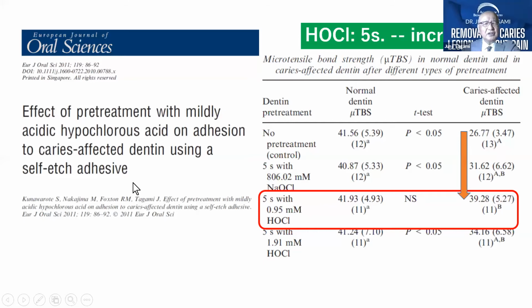Instead of the sodium hypochlorite solution, we tried to apply the hypochlorous water. And this is very effective to increase the bonding, even without the additional application of the reducing agent.